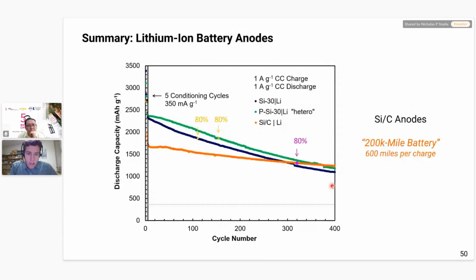There are many, many other people who are looking into synergistic combinations of silicon and carbon. So don't go full silicon, but just put a little bit of silicon in there. And what can you do with that? Our group has also been getting into that. And here's just a representative case of a really nice silicon carbon composite material. That one gets maybe 600 miles per charge, so something right in the middle of 400 and 800, and can last about 200,000 miles. So this cell has a different set of trade-offs. But at the end of the day, these data show us that even though silicon, on paper, looks like an easy material to beat graphite with, it's really still to this day extremely difficult to beat graphite.